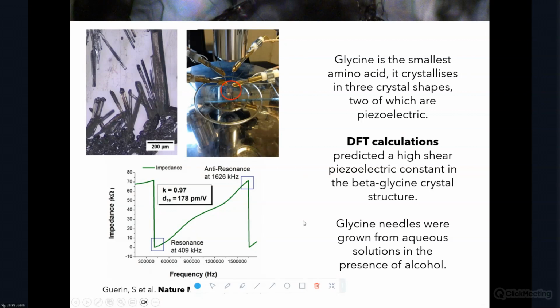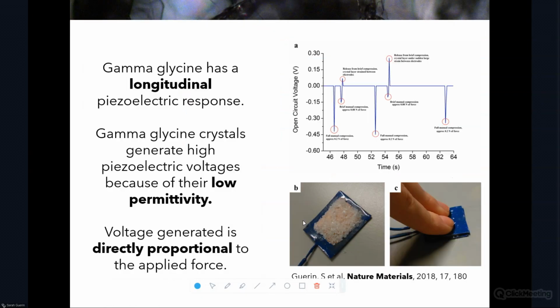Then the third polymorph of glycine is gamma glycine. This has really become our benchmark anytime that we're going in for a new application, because gamma glycine crystallizes in a unique space group among a lot of amino acids where it has a natural longitudinal piezoelectric response. Longitudinal means that you can have your electrodes on your material, as I've shown you in the other image, and you can apply your force along the same axis and then get your charge out longitudinally. So it's just the simplest form of device that we can make and the easiest to exploit for applications.